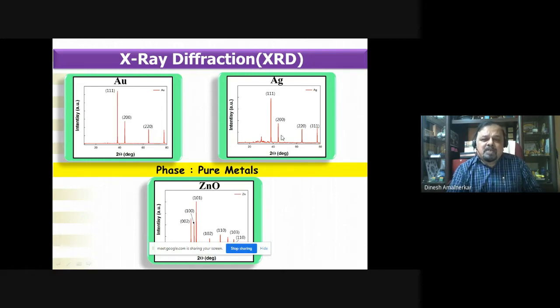So is the case with Roupyabhasma. In Roupyabhasma, we could again detect only the face-centered cubic structure of silver. There is phase purity. We did not find anything else in that. And the sharpness of the X-ray diffraction peaks indicates the highly crystalline nature of the bhasmas. But in the case of Jasadbhasma, what we observed, we never knew that Jasadbhasma is just zinc oxide, because Dr. Bendale said he starts with zinc ore as such and gets zinc oxide.